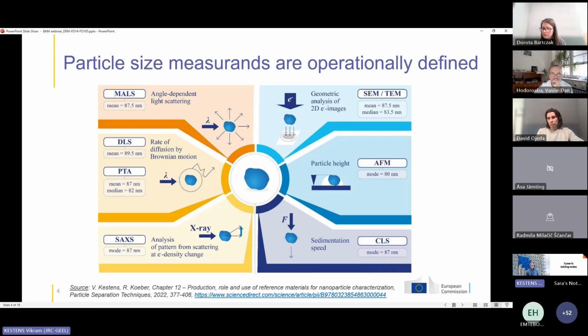Now, most of you know this, but I would like to remind you again about it. The fact that we use different methods to characterize the reference materials, the nanoparticles, is because these particles do not have a very spherical shape. They have a near spherical shape, but they are not perfectly spheres. And because of that, different methods basically measure the same particle, but they can give some different results, as can be seen on this graph here.